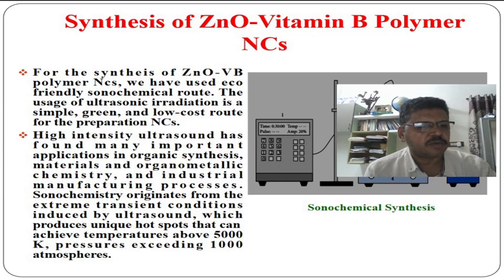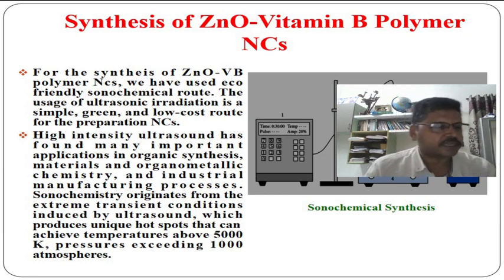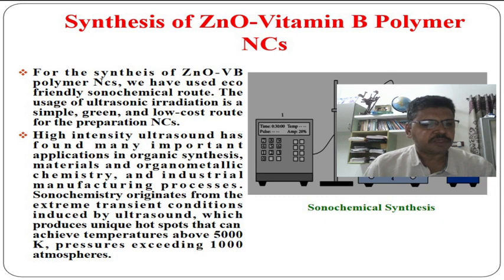In the next step, certain amounts of ZnO vitamin B1 nanoparticles in deionized water were dispersed, then sonicated for 50 minutes. In the last step, the prepared suspensions of modified nanoparticles were added to the prepared solutions of polyvinyl chloride and sonicated for 30 minutes. Then the prepared suspensions were moved to petri dishes and dried at 25 degrees Celsius to achieve the nanocomposite films. In the ultrasonic preparation of nanocomposites, the sonication was performed using a probe sonicator with a frequency of 20 kHz and power of 100 watts.